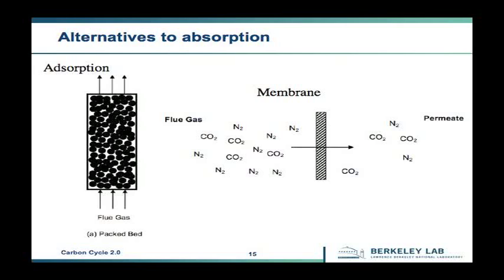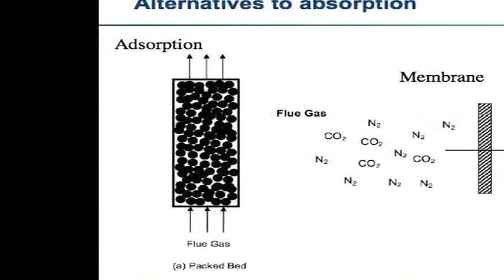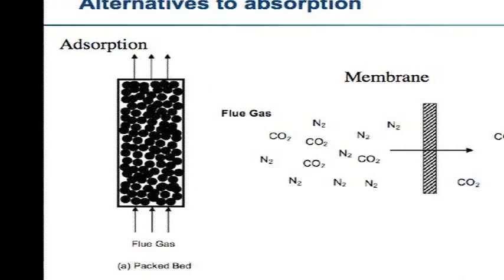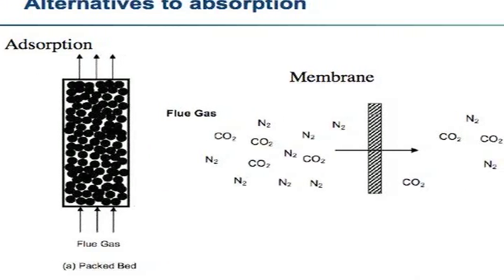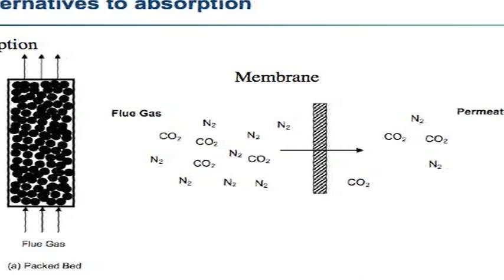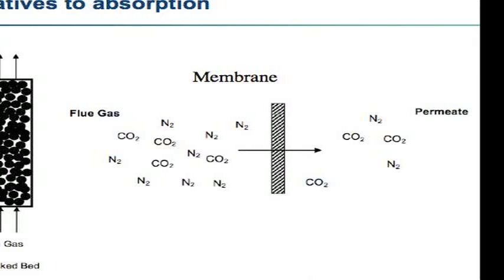So one of the ideas is you use a solid material. If you have a solid material, you put the same type of chemistry as you have in the amine solution inside those solid materials. The waste recycling of this water, which was consuming all the energy, you may not need, and you may do this process intrinsically much more efficient. And here is this membrane separation, where the driving force is actually vacuum on one side or increasing the pressure on the other side. And that is the energy penalty you have.